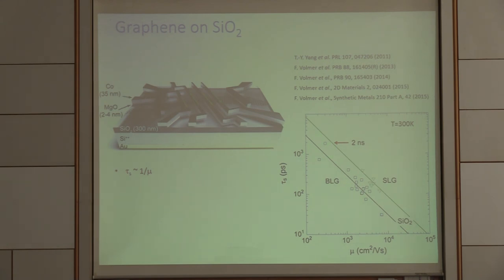The finding was, OK, there are single layer samples and bilayer samples. One can get reasonably nice values, but the bad side is that you have to go to very low carrier mobilities. And that's something one does not really want. This is surely showing that there's a lot not yet understood because the spin lifetime is scaling with one over the carrier mobility. So one would like to have values up here, but not in this corner here, because the diffusion lengths you can easily imagine is quite small here.